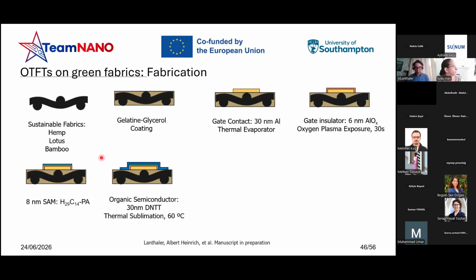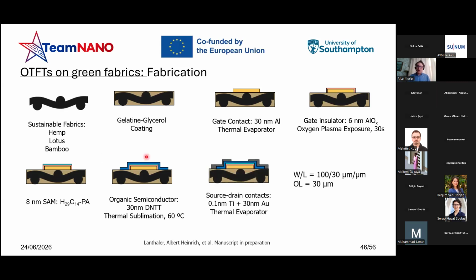of the thienothiophene, which is a very interesting organic semiconductor, peculiar for its stability in air, and which has shown very interesting mobility at around 3 centimeters squared per volt per second. Last but not least, the source and drain contacts were deposited through thermal evaporation. So first 0.1 layer of titanium, and then a 30 nanometer layer of gold. The final width-to-length ratio of the deposited devices is 100 to 30 micrometers, and the overlap is 30 micrometers.